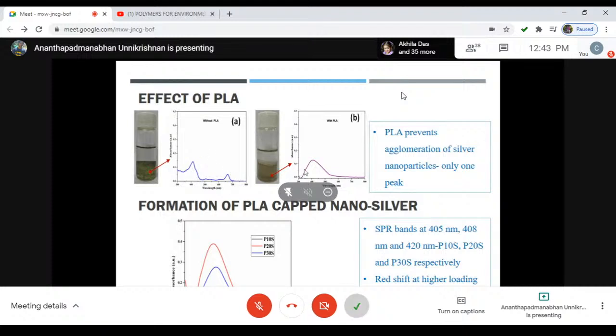But you can see in presence of lactic acid, you get only 1 absorption peak, which is an indication that PLA is a very good agent to generate homogenization within the system. We have peak 10, which means it contains 10% of silver. This contains 20% silver, 30% silver. But out of this, the 20% silver is the ideal one we have identified because of multiple reasons.